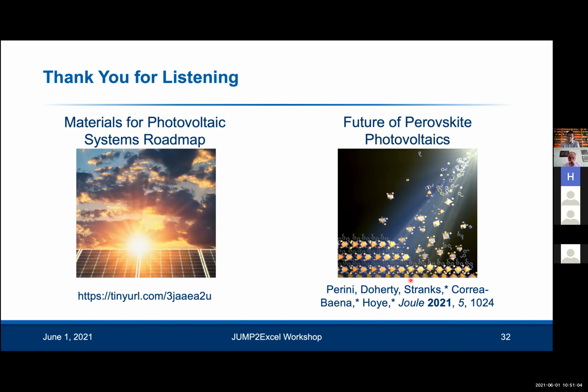But of course, for India, it's more a question of what tests you would do for new materials, because these tests have been developed for silicon, but new materials have unknown degradation pathways. If you look at the perovskites, that has only been developed for 10 to 12 years, and of course, it's not possible for people in that time to have a device outdoors and measure the performance over a 40-year period.